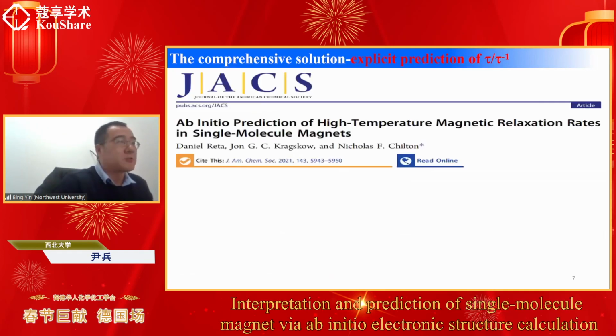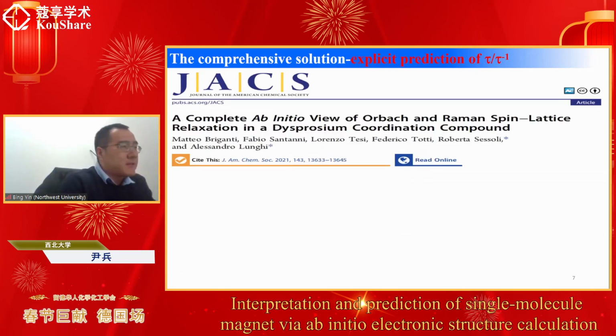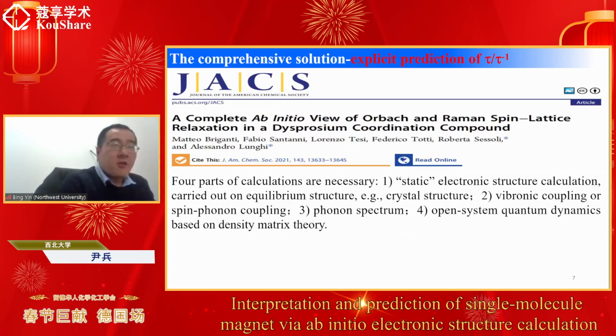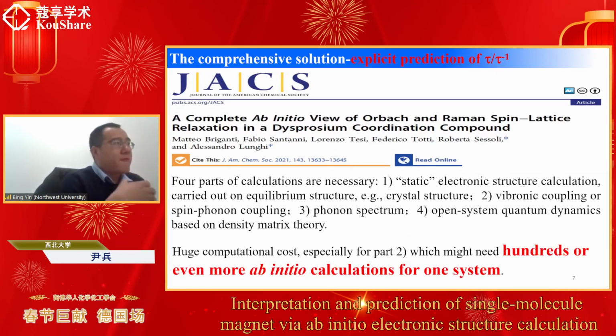For example, the method proposed by Professor Nick Chilton, as well as the method developed by Professor Lunghi. But their methods usually need four parts of calculation. The first is the static electronic structure calculation carried out on the crystal structure, then the calculation of vibronic coupling or spin-phonon coupling, then the phonon spectrum, and finally the open system dynamics based on master equation theory. Although very comprehensive, sophisticated, and accurate, the huge computation cost is unavoidable, especially for part 2, the calculation of vibronic coupling, which might need hundreds or even more ab initio calculations for one system.